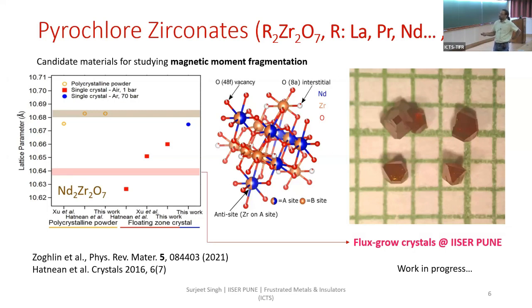growth of these materials was reported as early as in 2016 by the Warwick group. And they grew these crystals again by float zone, but using more powerful lamps, using xenon lamps. The issue is that since the melting temperature is around 2500 degrees centigrade, at such high temperatures, some of the neodymium evaporates, it goes away from the float zone. So this results in off-stoichiometry, and this off-stoichiometry is particularly bad because the neodymium is then replaced by zirconium. So in the common parlance, this is known as anti-stuffing.